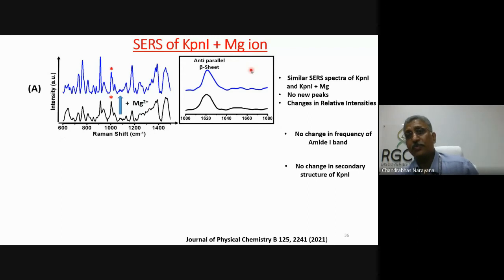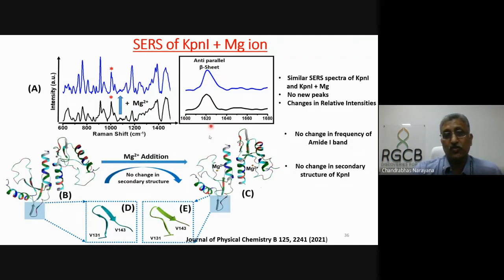Now, when we put the magnesium into it and compare the spectra, you see that the amide region doesn't change much. So there is no change in the amide region. So wild type is this. When you put the magnesium, we did the calculation, and we found that there is no change in the EDD region. So the magnesium binding into the EDD doesn't change the system. And this is the reason why these two behave promiscuously, because the structure function is similar to the wild type itself. So we could actually understand that.